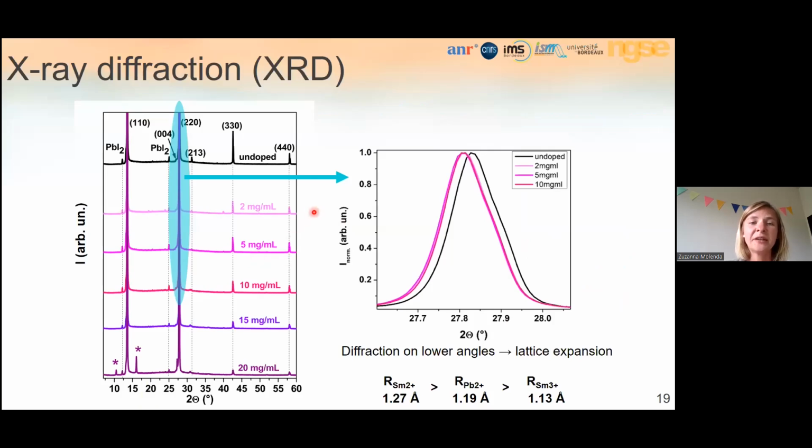So regarding other key properties of perovskites, here we have the XRD pattern, and it shows a typical MAPI tetragonal pattern that doesn't change upon doping, except for the highest doping concentrations, where we clearly can see some peaks that stand for most probably phase separation. And this probably stands for a decrease of conductivity for the highest doping concentration.